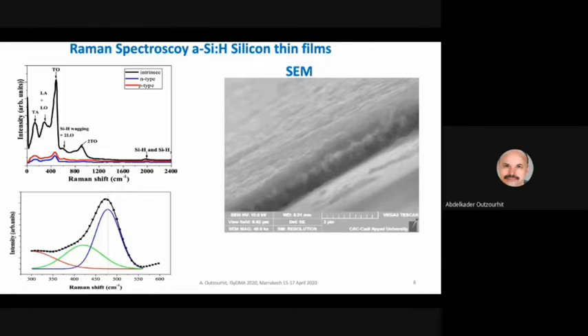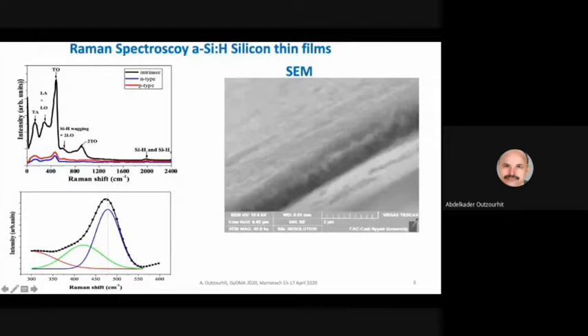In addition, of course, to some overtones of these peaks. That means harmonics of these peaks. How did we conclude that the films are amorphous? By analyzing this transverse optical peak, and by deconvoluting this peak, we observed that it's only made of one peak that is centered at around 480 centimeter minus 1, which is characteristic of amorphous silicon, hydrogenated amorphous silicon.